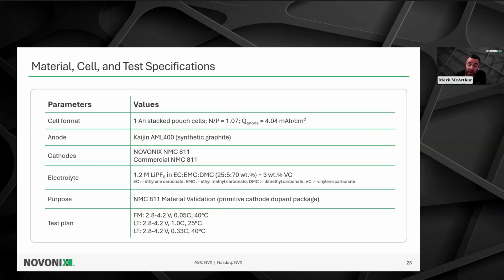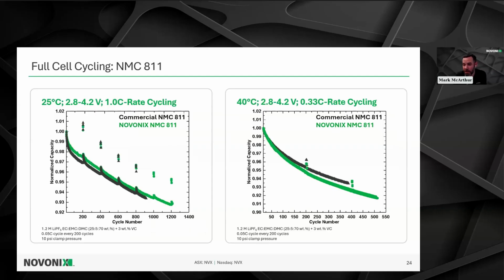And again, it doesn't stop there. What we do is take that material, we assemble 1 amp hour stacked pouch cells, just like in the 631 case, and we test under very similar conditions to the 631 case, only we decrease the upper cutoff voltage a little bit. Rather than going to 4.3 volts, we're only cycling to 4.2 volts. So I'm showing many, many more cycles here in the case on the left-hand side for 25-degree cycling at 1C rate, and on the right-hand side of the slide, 40-degree cycling at a C/3 rate. And you can look at the normalized capacity and you see that we are indeed quite competitive at both 25 degrees and 40 degrees to the commercial reference.